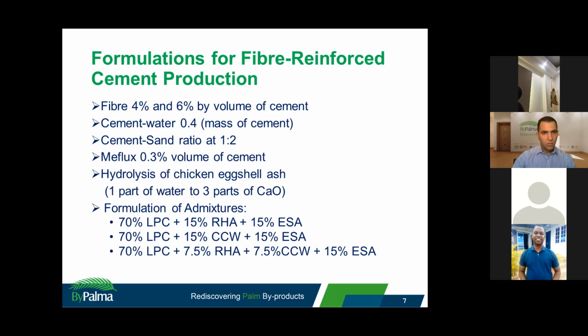Then, hydrolysis of chicken eggshell ash. Now, I need us to understand something again. I told us that the eggshell consists only of calcium carbonate. When you burn it at 900 degrees Celsius, it converts to calcium oxide. But because the eggshell ash is an expensive raw material, if you use it in a mixture, it's going to affect the composition of your composite. Therefore, we need to first of all hydrolyze the calcium oxide.